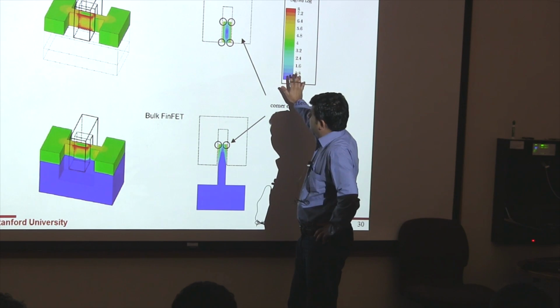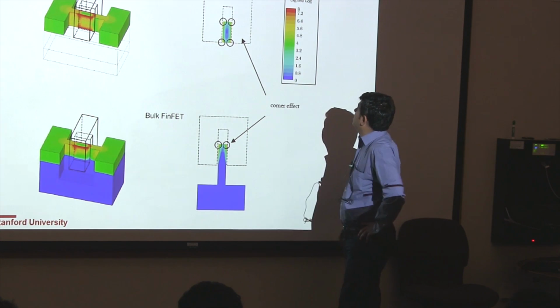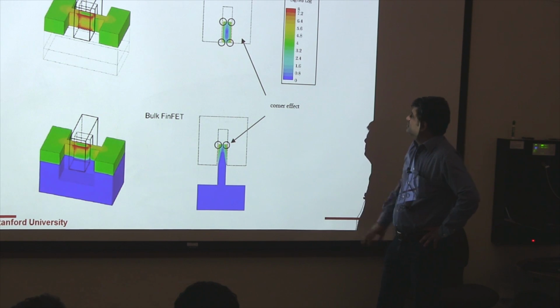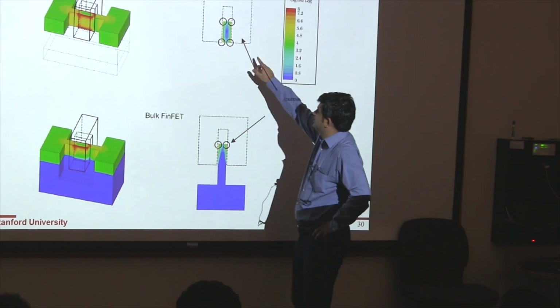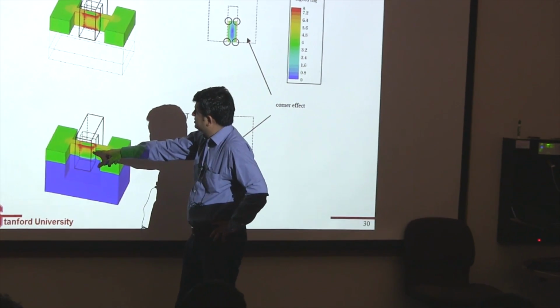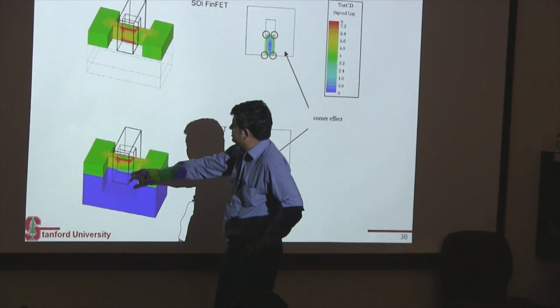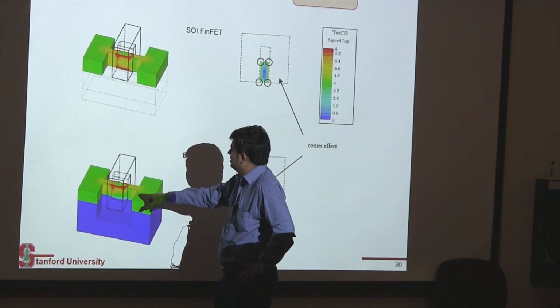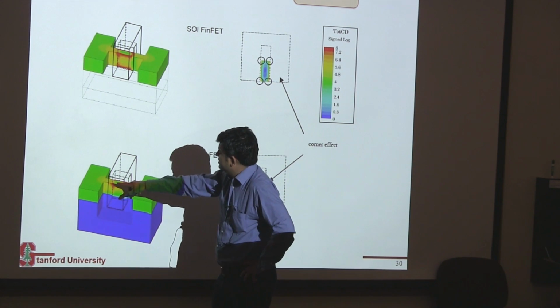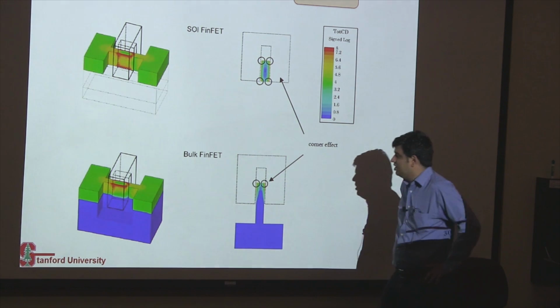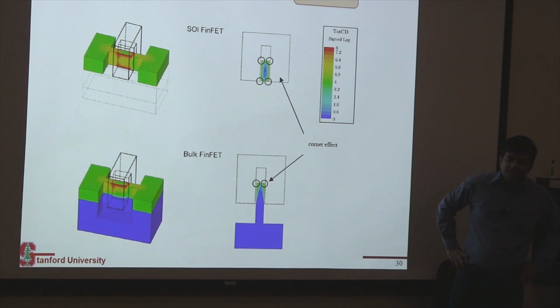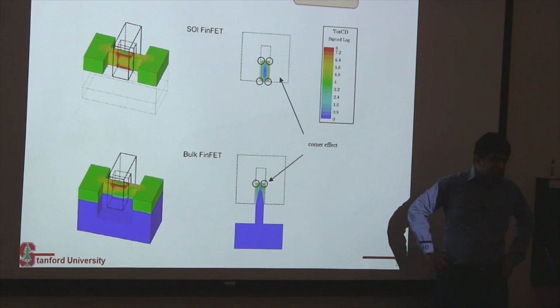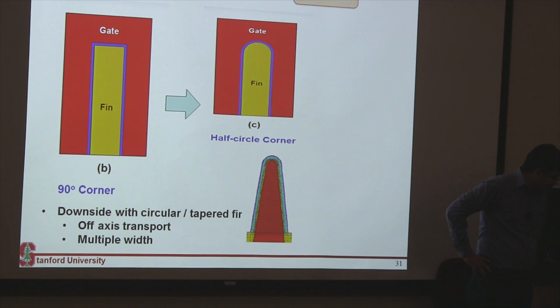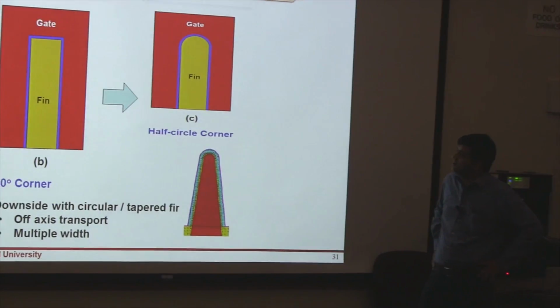So the corner of your fin always turns on faster. This is plotting the current density, in this case for a voltage near your threshold voltage, and you can see in both your bulk and SOI FinFETs you get current conduction happening through your corners when they should be really turned off. So this degrades your overall leakage, because at this voltage they should be really off, but because of these corner effects they are now turned on. We worked so hard to make this device, but because of these corner effects it's all ruined.